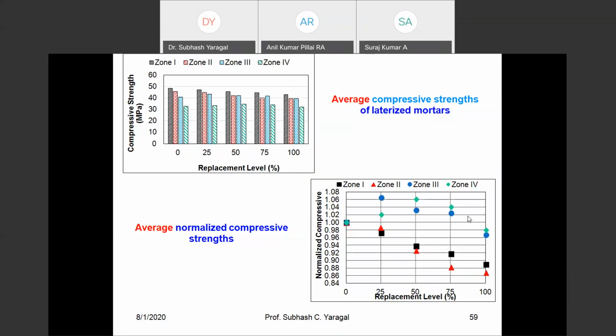So if you are looking at zone 3 and zone 4 sand, at 25% replacement, they are far superior to what you have got for the river sand. So straight away, if you are using laterized mortars, you can use zone 3 and zone 4. There is only plus or minus 2%, which may be due to experimental error. So for zone 3 and zone 4 sand, which is characterized, you can use lateritic sand to the extent of 100% without compromising on the strength of your mortar.